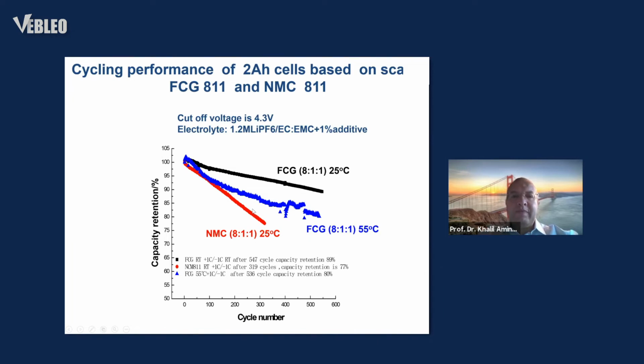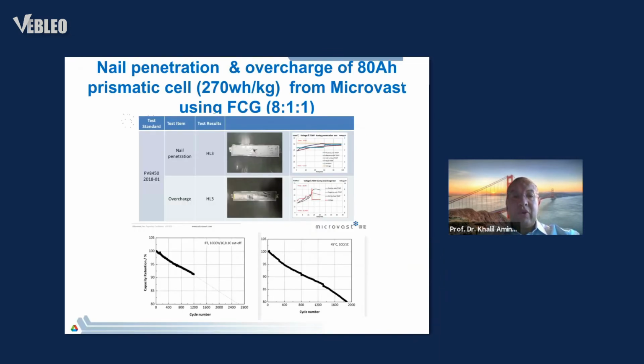So this is a technology that's been licensed by Microvast, and they have scaled up this material, and they were able to achieve almost 280 or 290 watt-hour per kg with this technology, and it is actually being produced for use in electric vehicles. In this case, it's 270 watt-hour per kg. So you can see clearly they pass all the safety tests. This is a very large cell. They pass the overcharge. They actually have better performance than us when they put it in a full cell, because they are much more expert in building electrodes and all that also.